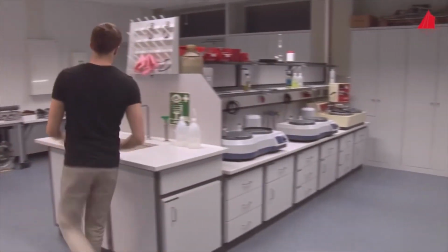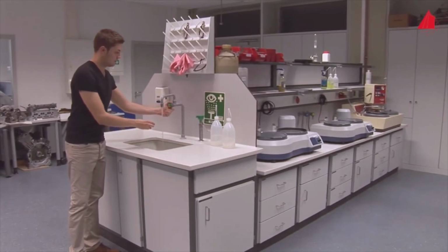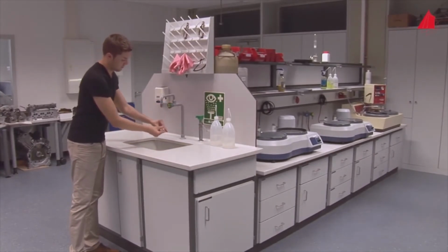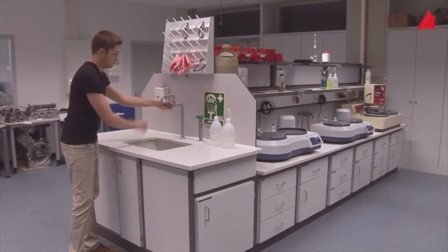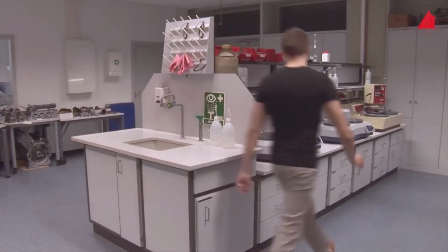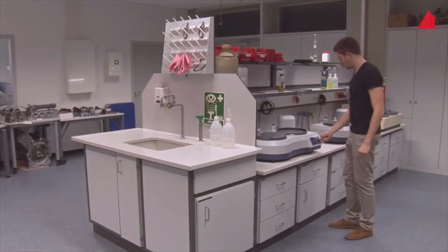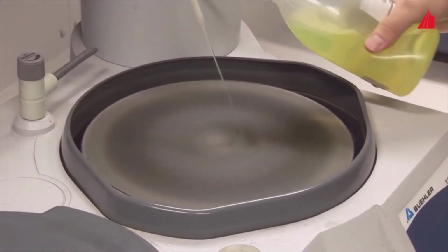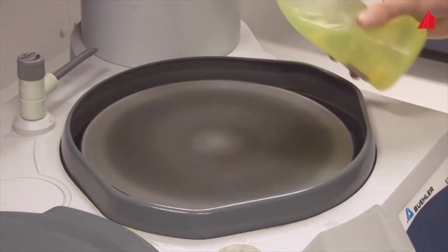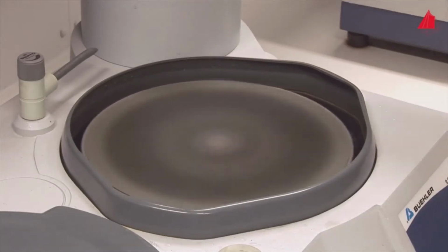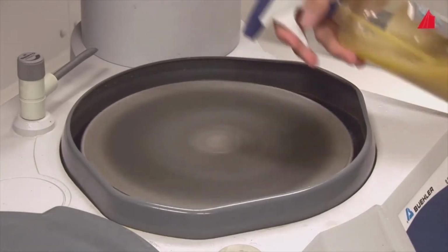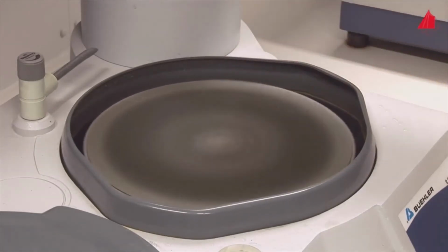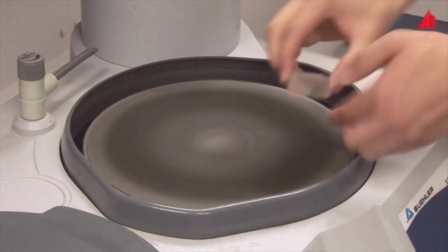Hands should be washed as well so that no unwanted particles find their way to the sample and the polishing cloth. Now the material tester can start with a first polishing operation. He chooses a polishing disc equipped with hard cloth of low resilience, moistens the cloth with a suitable lubricant, and adds 2 splashes of diamond suspension of particle size 6 micrometers.